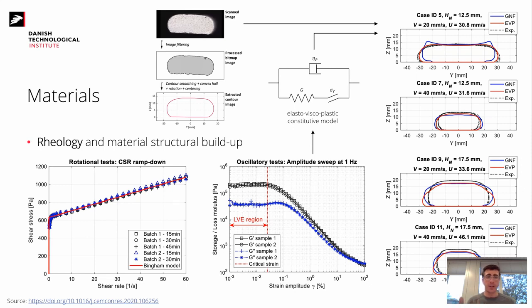So we validated and recently published this. I have a link to the source, and I'll share this presentation at the end of the event. We validated a CFD model that describes the shape of extruded layers. And the benefit here is that now, instead of making 10 or 15 trial prints, I can reduce the number of trial prints in the lab by only making the material characterization and relying on numerical simulation, to optimize the number of tests I have to do in order to identify a mix that's first printable. And then comes the second part now.